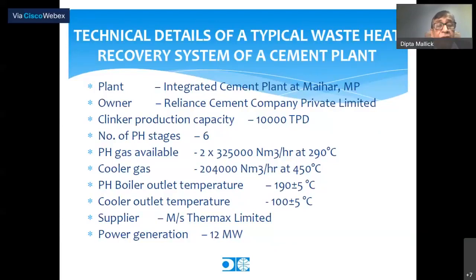We have given the figure 2 x 325,000 Nm³ per hour at 290 degrees. Cooler gas 204,000 Nm³ per hour at 450 degrees centigrade. The beauty is that the PH boiler outlet temperature was 190 degrees centigrade, because that's what was desired by the raw mill dryer plant. So from the PH, we are getting a delta T from 290 to 190, which we can fruitfully utilize. The cooler outlet doesn't have that much function to do, so we can reduce it to as low as possible. 100 degrees centigrade is the lower boundary.